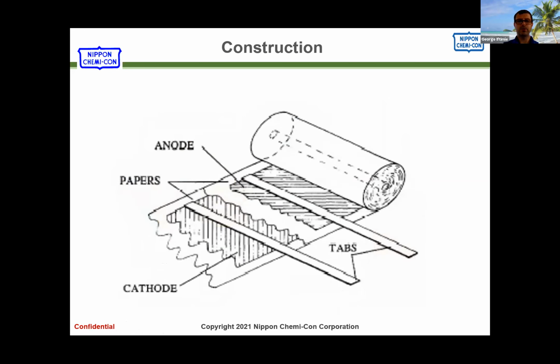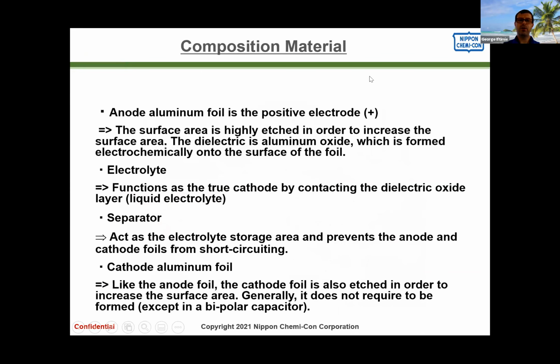Again, this is just a way to connect the tabs. So you have the anode foil, which is of course a positive electrode. This is basically where a lot of your capacitance is coming from. It's a very highly etched surface, and then you have the aluminum oxide. Electrolyte is really the true cathode, not really the cathode foil.